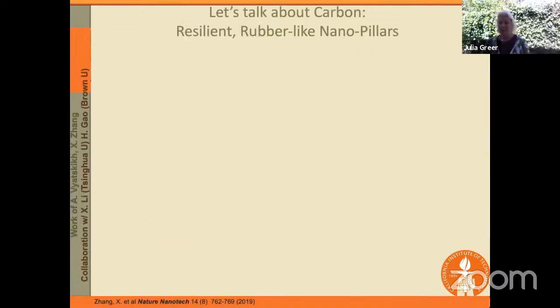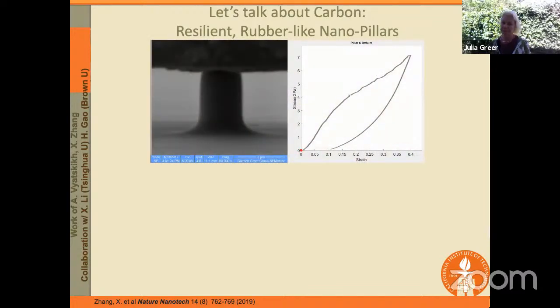Okay, so because it's all about defects, let's talk a little bit more about them, and let's use carbon as our model material. So what we made here is a glassy carbon, so you know, a pencil lead effectively, pillar. This particular one is on the order of 1.6 microns or so, and we're compressing it. Now, you all know what happens if you push really hard on your pencil lead. Of course, it's not compressible, and it starts shattering.